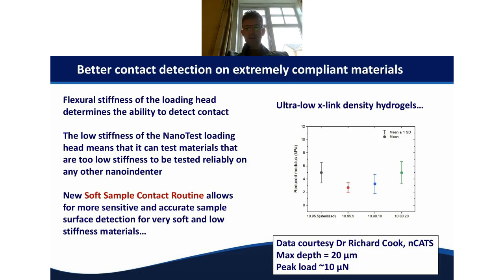And if you look at how the nanotest stacks up against any other nano indenter, you'll find actually we're uniquely suited to very accurately measure these low stiffness materials. So we have a very low stiffness loading head, so consequently that means that we can detect low stiffness materials more easily because they're a bigger fraction of that total loading stiffness that you're measuring.